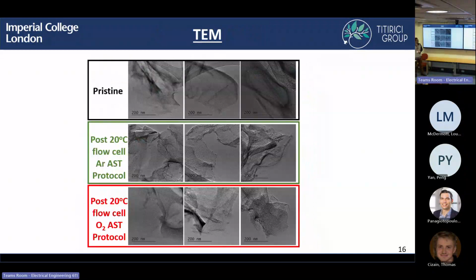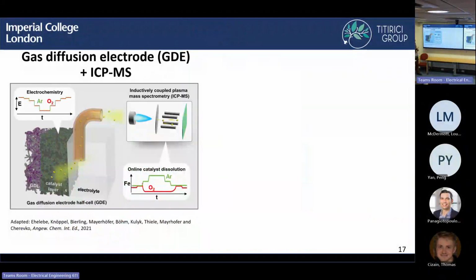And looking at post-mortem characterization, we couldn't really see any large particles of iron after this AST protocol in argon or oxygen. And so from these kinds of measurements, it seemed like there wasn't really too much difference going on between the argon and oxygen measurements. And so what we wanted to do was try and test this in a more practical device.